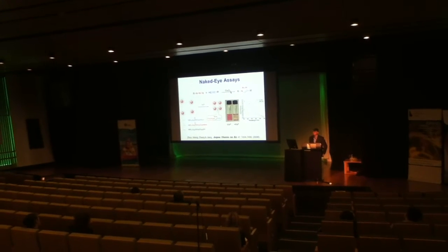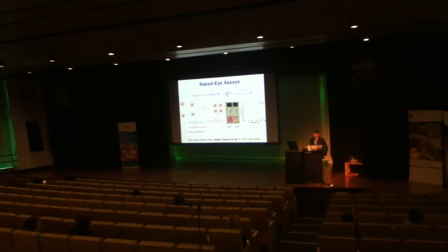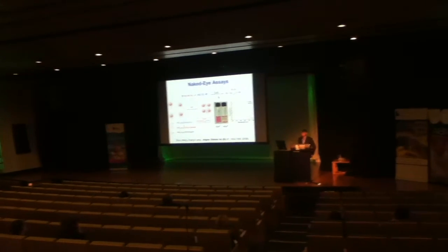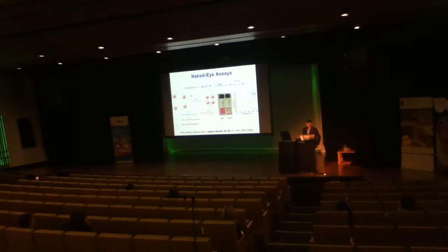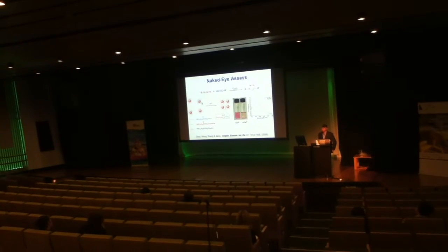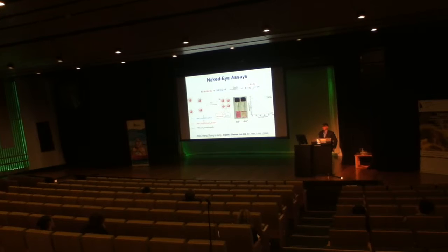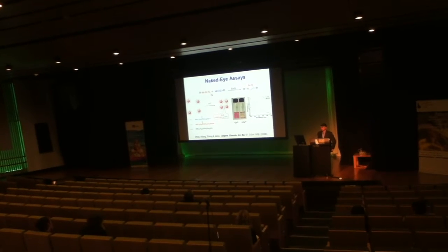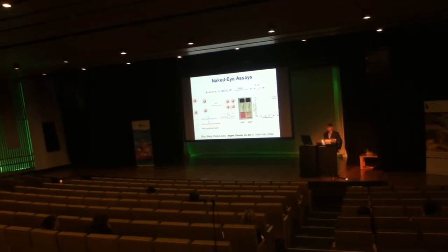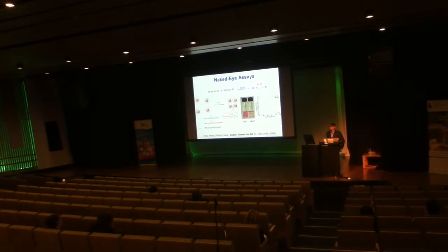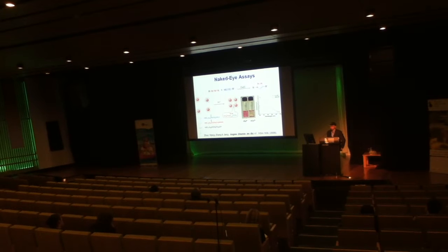So this reaction has been used to tether a lot of these molecules together. But our thought is to actually use this reaction to detect copper. The design is to actually put these two ligands on the surface of different gold nanoparticles, and if there is presence of copper, because of the reaction that would tether the gold nanoparticles together, and because at very low concentrations, gold nanoparticles, depending on whether it's dispersed or it's aggregated, the color is very different.